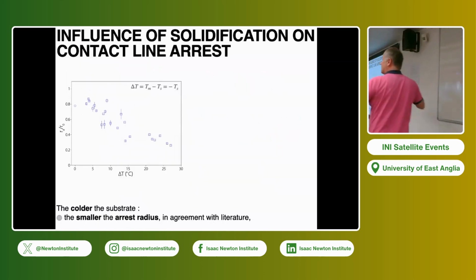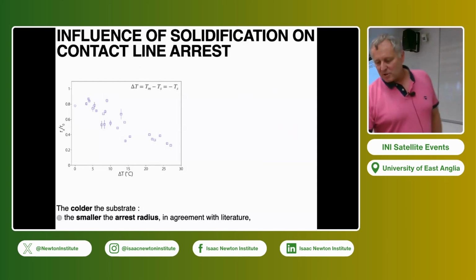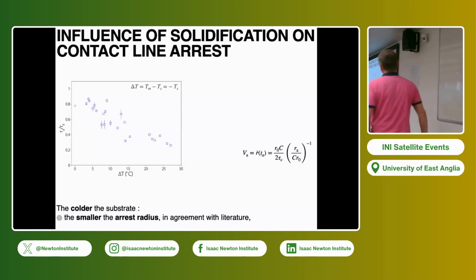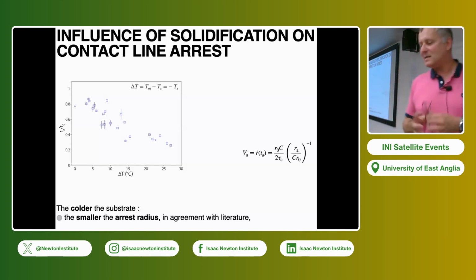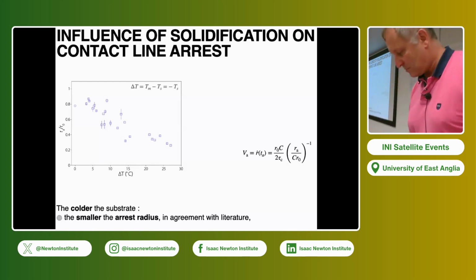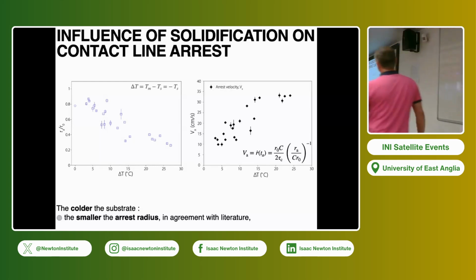So actually, we can measure the final radius, what we call the RS radius, and if you measure this RS radius as a function of delta T, you have a decreasing function, as we have seen in the movie. And by making some algebra, you can make this RS radius correspond to an RS velocity, which will be the velocity of the spreading dynamics at this radius if it was not stopped. If you do that, you can associate to any RS radius an RS velocity, which in that case is increasing as a function of delta T.